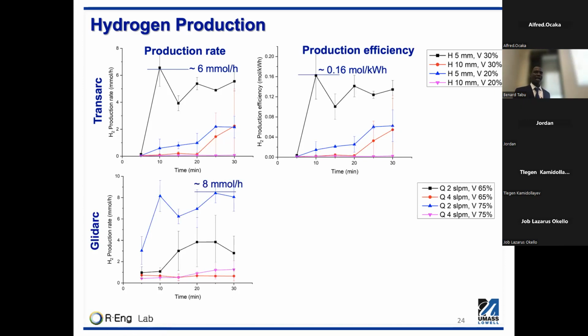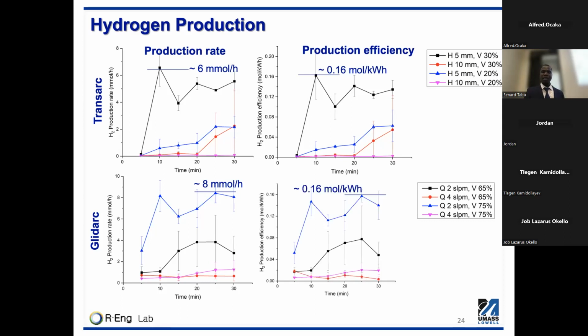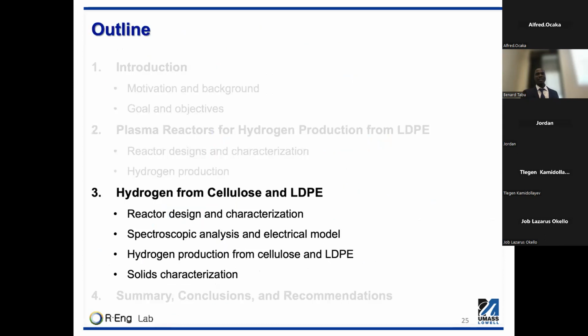And this is for Glidarc. For Glidarc, we see that at a lower flow rate of 2 SLPM and higher voltage level, the production is much higher. Still, it increases within the first 15 minutes and tries to level off. And the hydrogen production efficiency follows the same trend. But overall, in these results, we see that the hydrogen production in both cases, the transfer arc and Glidarc, are comparable. So with this, we move to the next, the second last aspect.